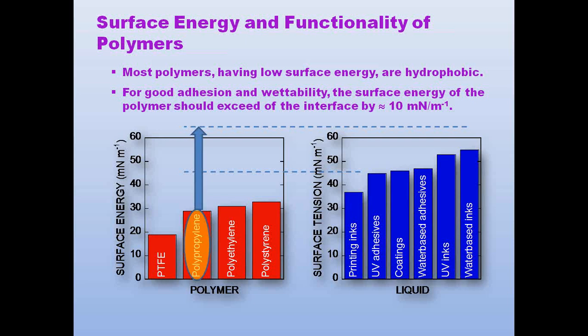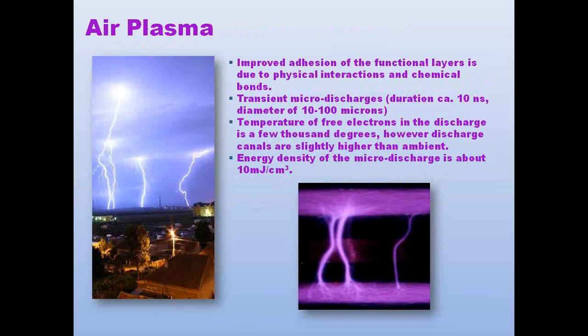One of the first methods, and one of the more inexpensive methods, of creating this type of adhesion is air plasma. Air plasmas rely on the discharge of energy from an electrode that will create a change in the surface of any type of material. It does so by initially avalanching some micro discharges through what are known as channels. The duration of those micro discharges is about 10 nanoseconds. They have a diameter of 10 to 100 microns. You may realize as well that the temperature of these micro discharges is quite high, usually a few thousand degrees centigrade.